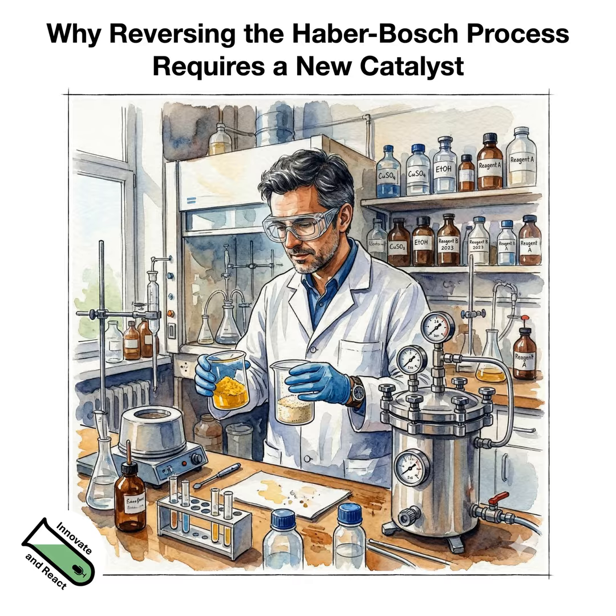Yeah, definitely. I also used ruthenium in my PhD research for amine synthesis. So it's also this nitrogen compound in there. And there it was also always the challenge that you could find a very great catalyst, but to bring it to the industry, ruthenium usually is too expensive. And that is also, I think, the case for this reaction. Maybe for the small-scale reactors you mentioned before, the ruthenium catalyst might be viable, because you don't need as much. But if you want to do it on large scale, you need huge amounts of catalyst, and then ideally a cheap catalyst. And then the iron would be ideal, but it's not as reactive.